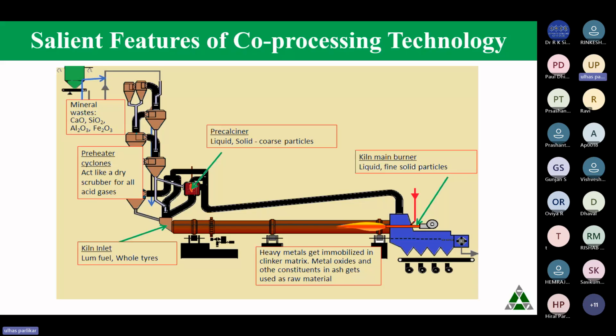But all these acidic gases, excepting the nitrogen oxides, will get trapped in the lime, which is used as raw material in cement manufacture. Lime is a highly basic material, and all these are acidic materials. They react in this 150 to 180 meter tall preheater tower that we talk about, where we have a countercurrent exchange of heat from the hot gases to the cold material coming down. That's where the reaction happens and all the acidic material is trapped. So in the emissions, there's absolutely nothing.